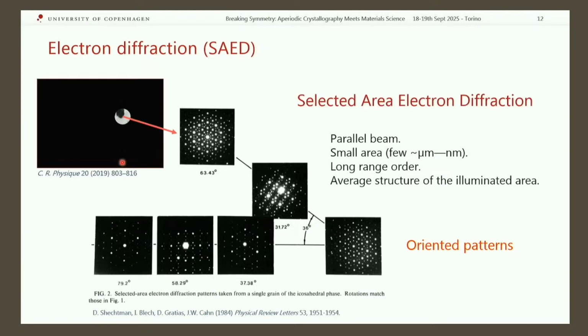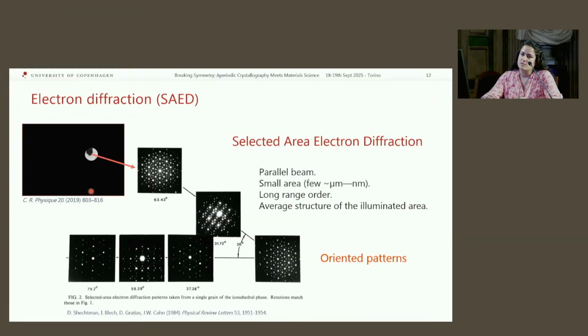We can insert a physical aperture in the instrument to delimit the area where we want to collect the diffraction pattern, because the diffraction is caused by the average of all the scattered electrons from this region. So it's giving us average information, which is actually its strength. And we can precisely control the orientation of our sample, to find the orientation that gives us the most symmetric patterns. And again, this is how the quasi-crystals were discovered, with selected area electron diffraction.